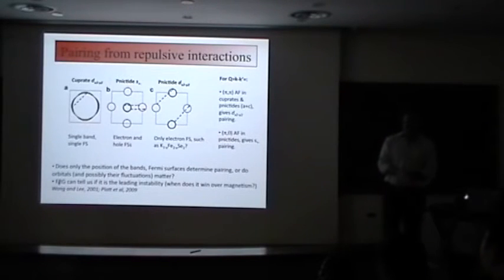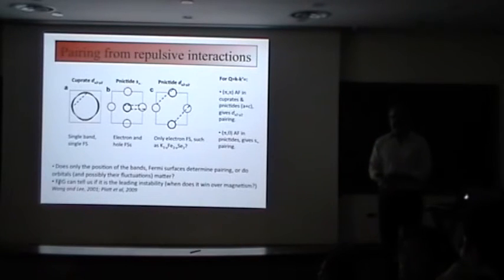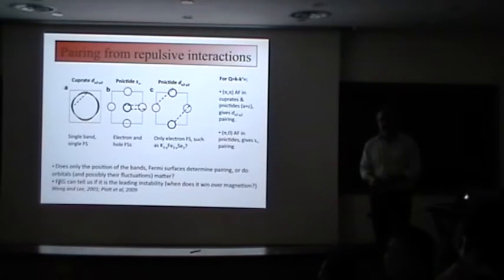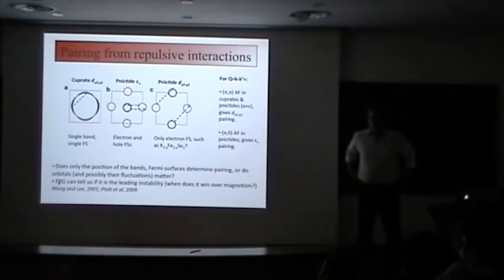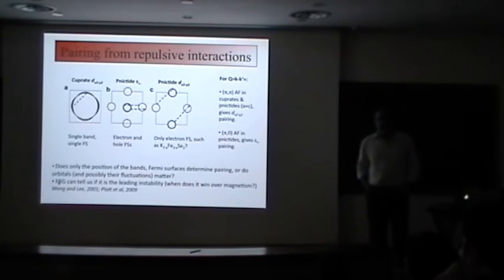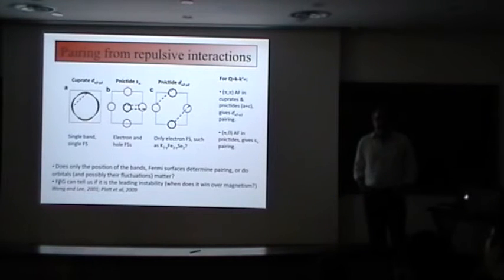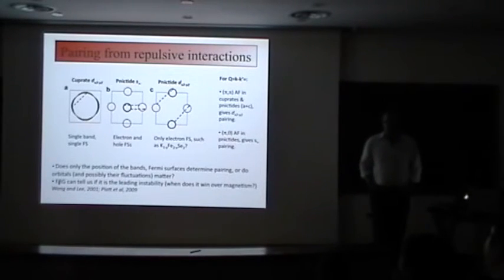Yes, so you talked today about these two transitions, the orthorhombic and the magnetic transition. And the phase diagrams that I think you showed, and some previous speakers showed, it seems like these two transitions sometimes happen at the same point, sometimes they appear at different temperatures, and there are compounds where, in the undoped situation, they are at the same point, and as a function of doping they split.